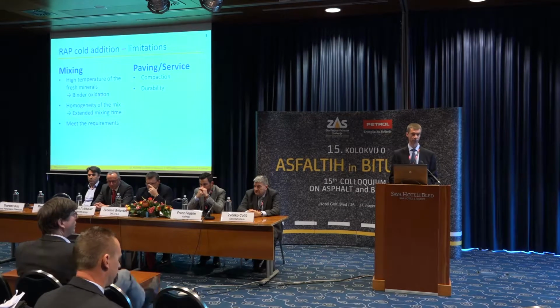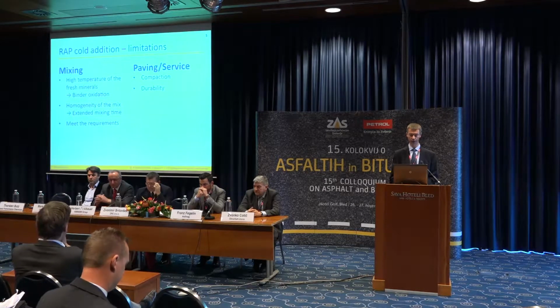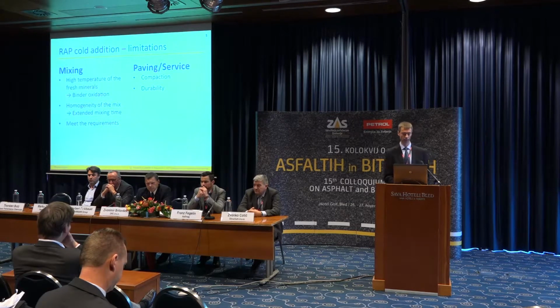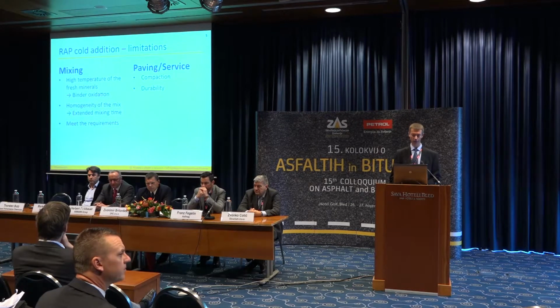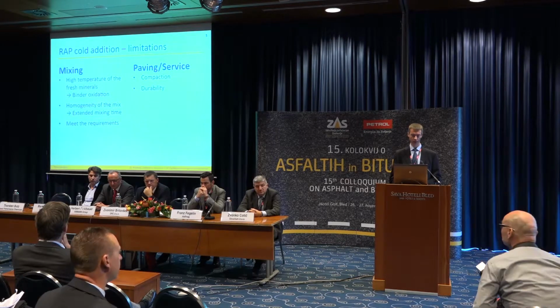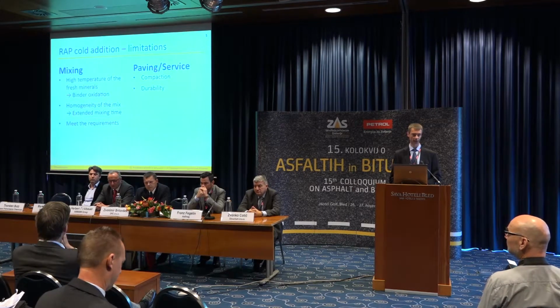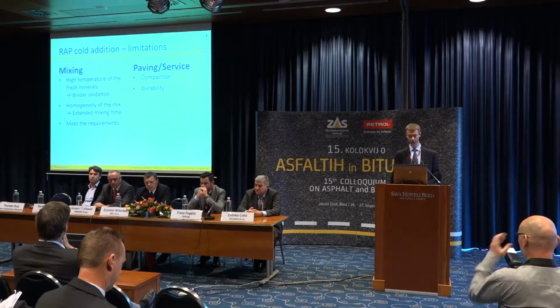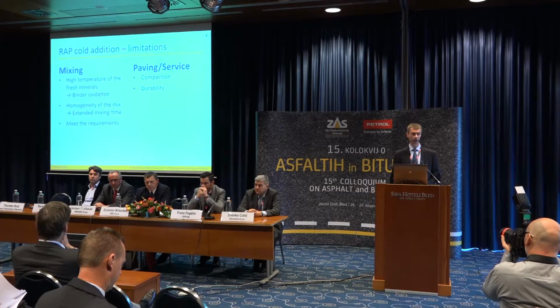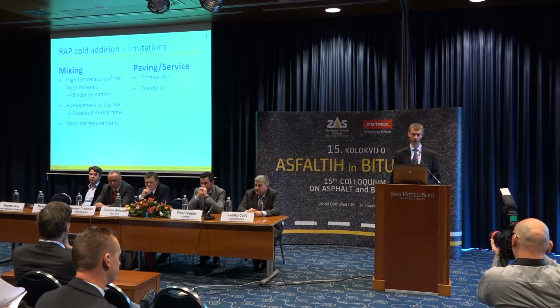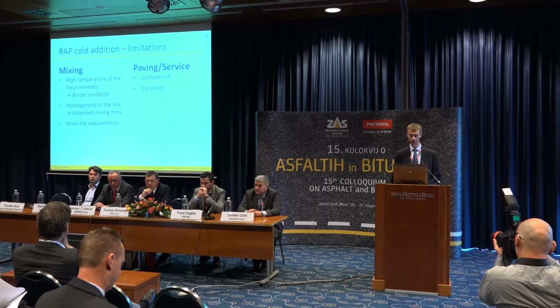The cold addition of RAP has some technical limitations, and therefore only up to 30% are possible. The energy for heating up the RAP has to be transferred from the fresh aggregates, which have to be heated higher than normal. And this high temperature can damage the binder in the RAP, for example, by oxidation. Another limitation is the moisture in RAP, which releases high volumes of water steam, which may cause technical problems in the mixing plant and also with the emissions of the plant.